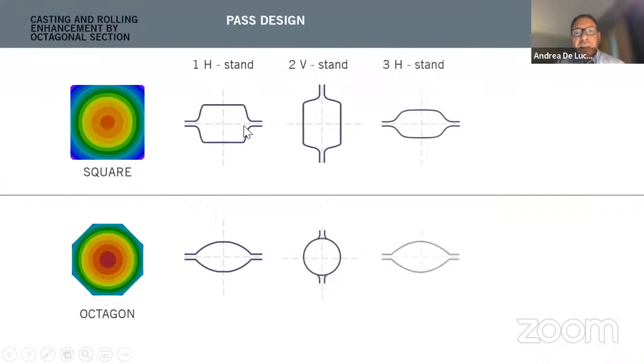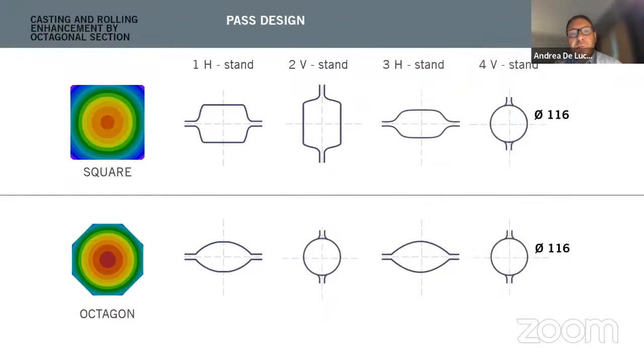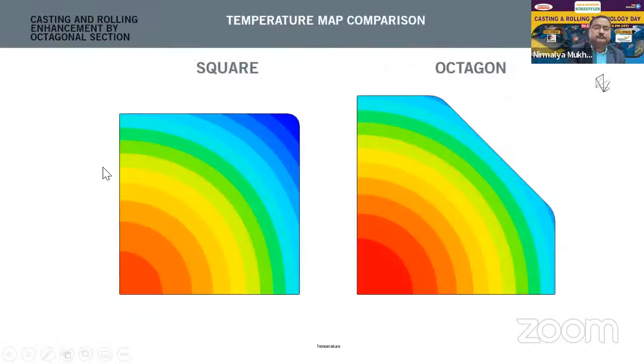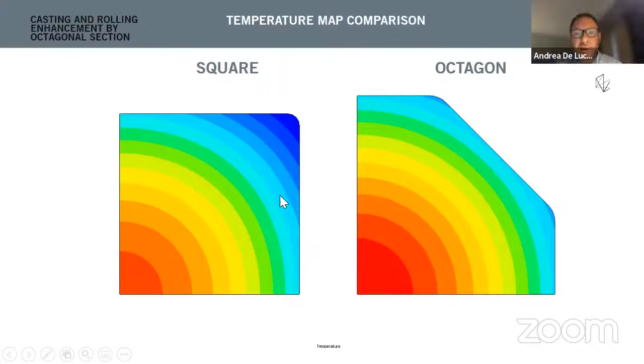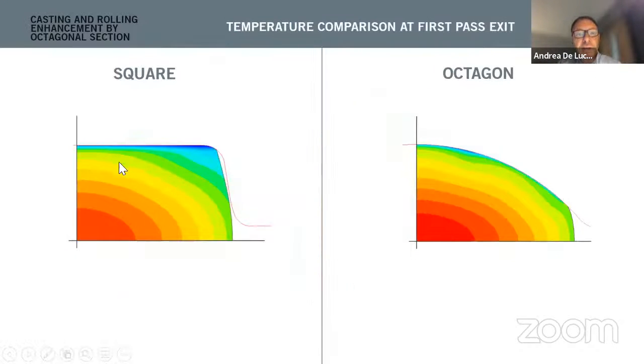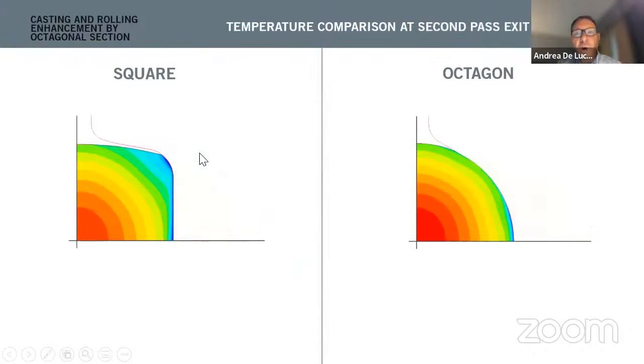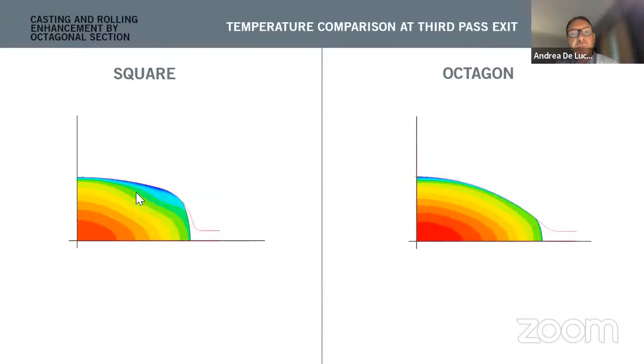The octagon is not only helpful in the casting machine, but also in the rolling mill, because the temperature is much more homogeneous and the roll pass design is more similar to round and oval passes, which helps reduce the differences in temperature between the surface and the central part of the billet. As you can see in this simulation, from the square to the octagon, the difference in temperature between the surface and the center is very limited.